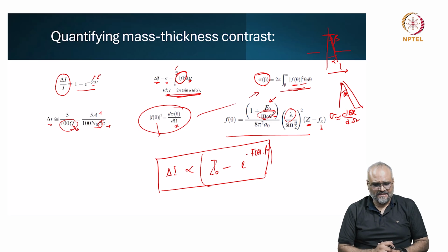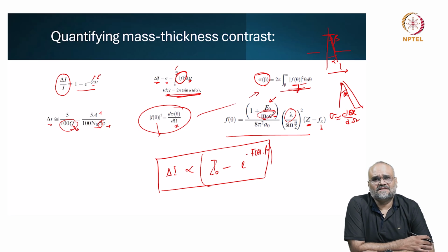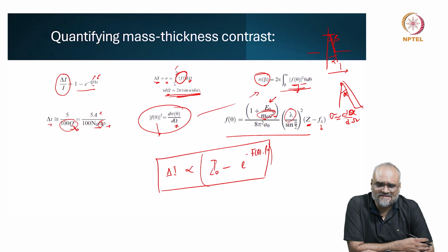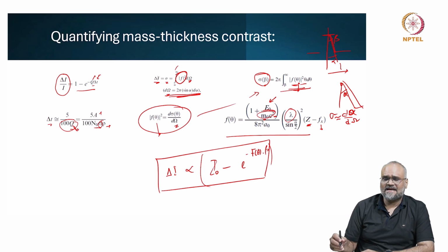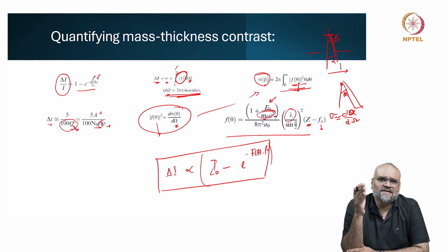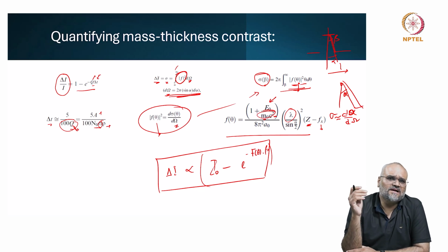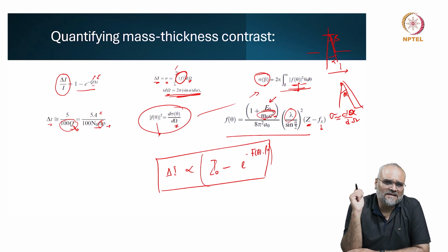You can also see that as the intensity variation is dependent on the structure factor or the atomic scattering factor, if I have a grain which is oriented along a specific crystallographic orientation, you call this as orienting the specimen along zone axis, you would see that the path of the electron beam as a consequence of Bragg's diffraction is confined to a very specific path, and the angles of scattering are also well defined. So, this results in what is called as channeling contrast as well.